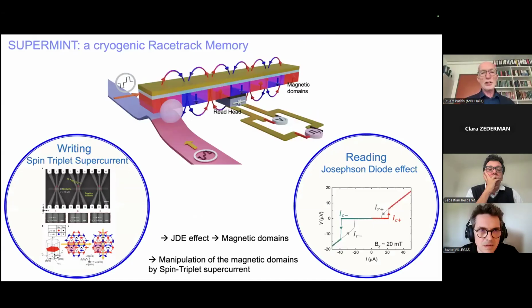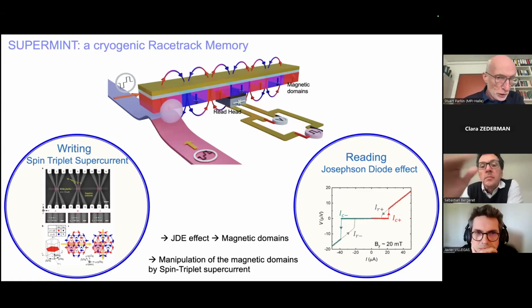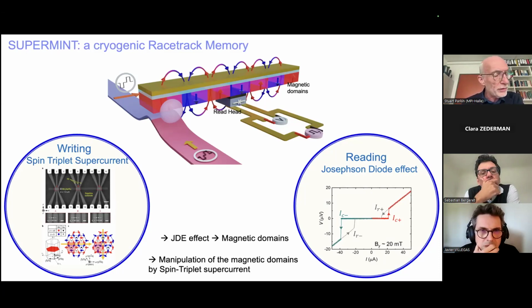And now finally, I wanted to mention, well, our goal is now to use these two concepts. One, we want to create spin triplet supercurrents in the S equals 1 or S equals minus 1 state and inject those into a conventional racetrack, although maybe from special magnetic materials, in which we could move the domain walls using the angular momentum from the spin triplet supercurrent, which in principle will be very energy efficient. And at the same time, we want to build this Josephson diode into the racetrack, e.g. using the platinum-based diode, and then we can detect the domains from whether or not a supercurrent flows through the diode formed between the racetrack and this platinum junction.